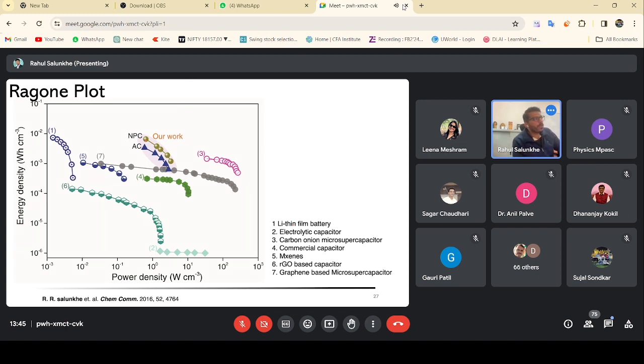So if we see our work, we can see that it has very comparably high performance compared to that of the lithium thin film battery, electrolytic capacitors or the carbon onion capacitors. But we can see that these carbon onion capacitors have very high specific power. Because they are zero dimensional, the ions come and go very easily, abruptly on the surface of the material. That's why it is hard for our material to beat these carbon onions. Our material is a three-dimensional material, and it's very difficult to remove the ions very quickly compared to that of the carbon onion materials.